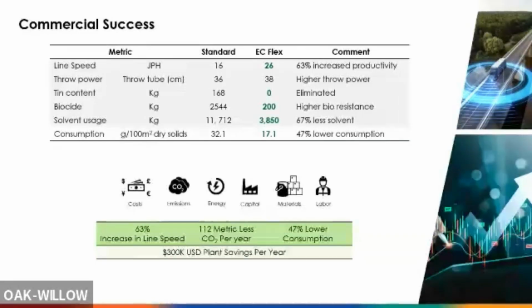All right, so here's an actual cost-saving example. This particular customer, we did a pour-over conversion. That means stop feeding the old material, start feeding the new material, convert the technology. It takes about 90 days. And they were able to deliver. First, they were able to increase their line speed 63%, right, just by going to a lower cure material.